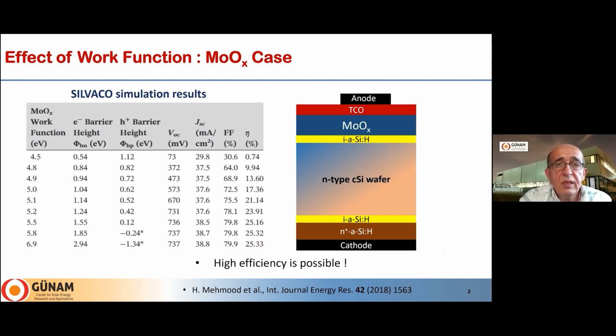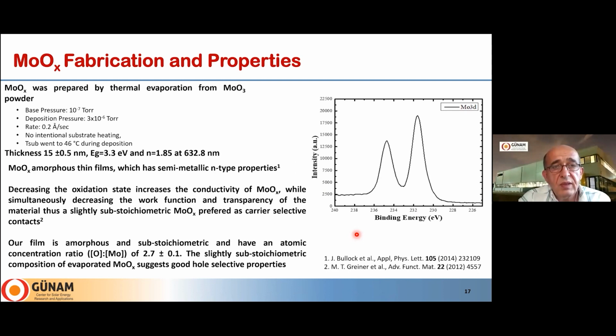The structure we simulated consists of molybdenum oxide on one side. On the other side, we still have the standard N-type heterojunction made by standard N-type amorphous silicon. Of course, we studied molybdenum oxide in detail. We looked into the chemistry of the material we fabricated, and we developed a thermal evaporation methodology to fabricate good, uniform, and well-controlled films on silicon. And the thickness can be controlled below 1 nanometer, as you see.